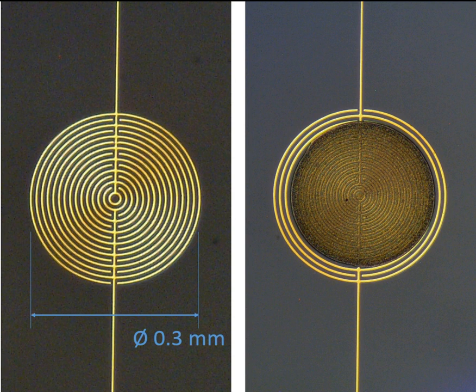Firstly, the stability of the gold nanoparticles depends upon the integrity of the SAM, which prevents them from sintering together. Secondly, the SAM of organic molecules defines the separation between the nanoparticles. For example, longer molecules cause the nanoparticles to have a wider average separation. The width of this separation defines the barrier that electrons must tunnel through when a voltage is applied and electric current flows. Thus by defining the average distance between individual nanoparticles, the SAM also defines the electrical resistivity of the nanoparticle assembly.